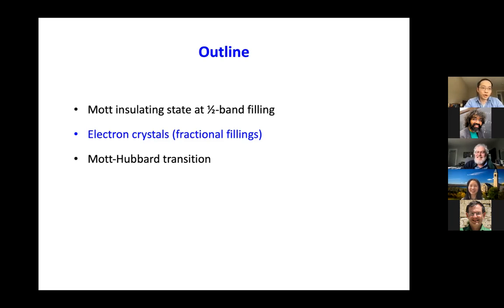Hi, Jie. I have a quick question. As compared to the graphene bilayer, in these materials like tungsten selenide, they also have very strong spin-orbit coupling. I was wondering whether the strong spin-orbit coupling and the broken inversion symmetry, so you have lifted spin degeneracy, will give the Moiré band some non-trivial topological nature. Yeah, that's an excellent question. That's something we and others have been searching for. It turns out the first Moiré mini band is quite isolated from the rest, so it's not topological.